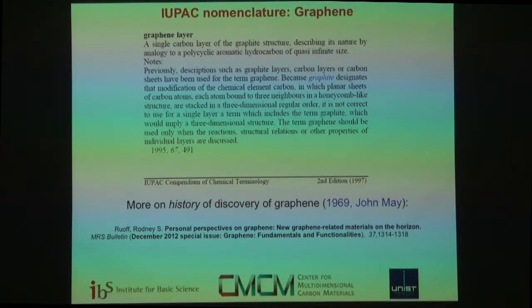So it's quite fascinating, sort of a back to the future story, because now, we and the worldwide community would love to have very fine control over the degree of misorientation between the layers, because the symmetry influences certainly the physics and perhaps the chemistry in interesting ways. In fact, I'm quite sure it will influence interlayer chemistry, obviously, if you change the interlayer registration between the atoms.